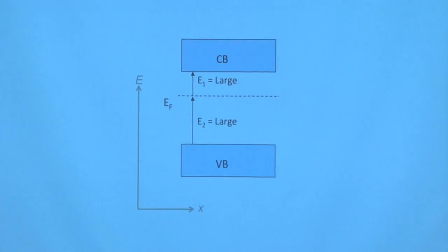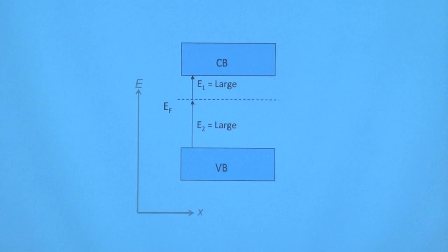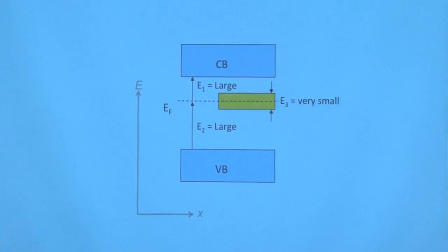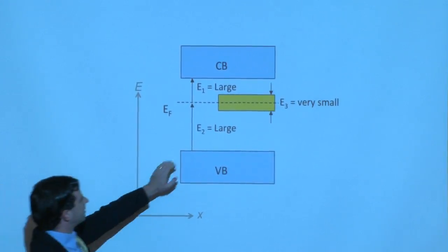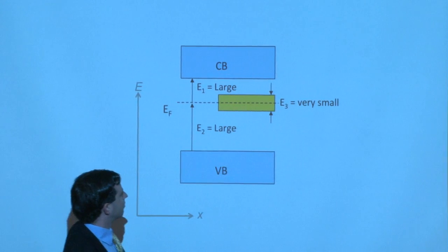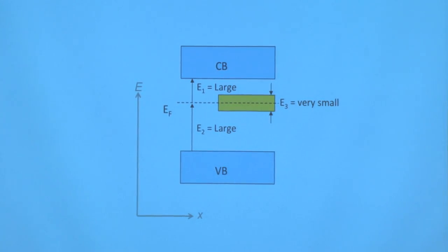But now, by doping the material with a specific type of dopant that forms mid-gap states, we're going to create a new energy level here that is partially filled. We can then excite with relatively little energy carriers into the excited states within that orange band, and they can transport charge throughout the material.